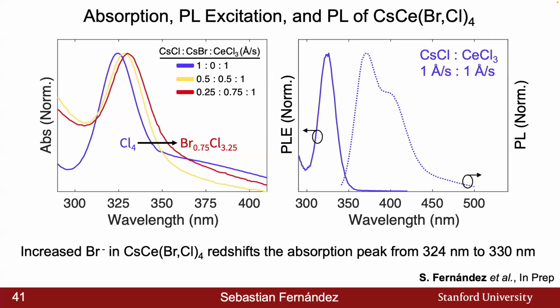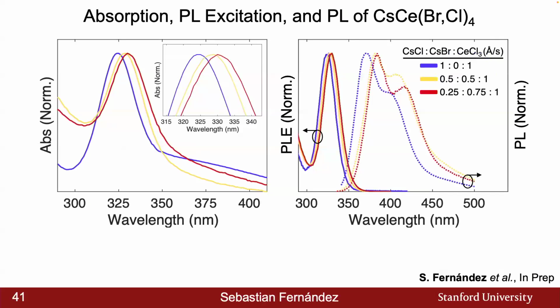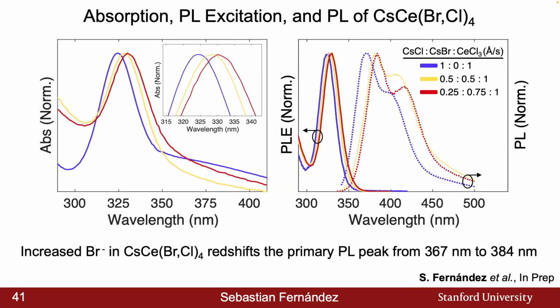And it turns out as we move from a pure chloride to a mixed bromide chloride, we get, as we expect, a redshift in the absorption peak from 324 to 330 nanometers. As well as we can see more clearly within the inset here, as well as similar trends within the photoluminescence excitation spectrum, we can also see from the photoluminescence of the thin film that we can move from 367 to 384 nanometers, really showing the tunability from using the cerium chloride-based precursor.